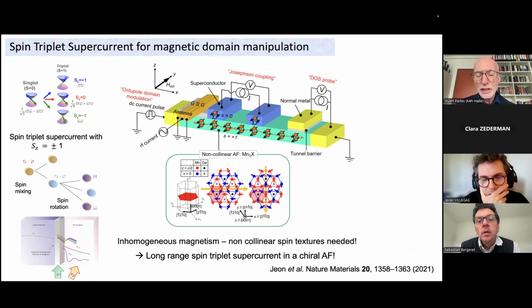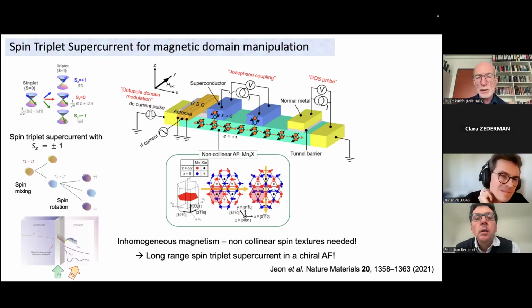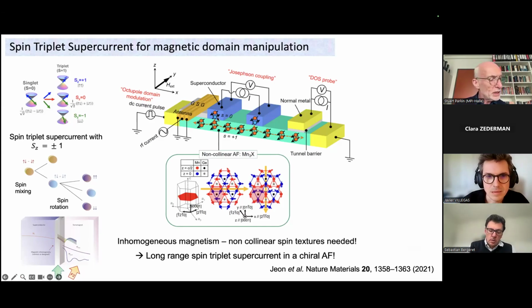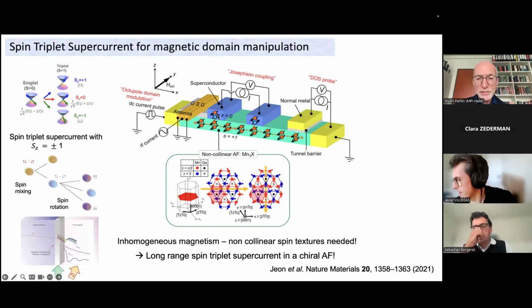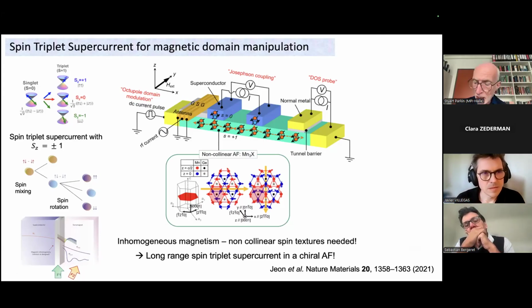And what does that mean? That means that what we demonstrated, and this is work by Kun Rok Jeon, who was a postdoc in my group, who's now back in Korea, was that we could place these blue niobium electrodes, by electron beam lithography, on top of a layer of manganese-3 germanium, which we grew by sputtering, and we showed that we could pass a supercurrent long range